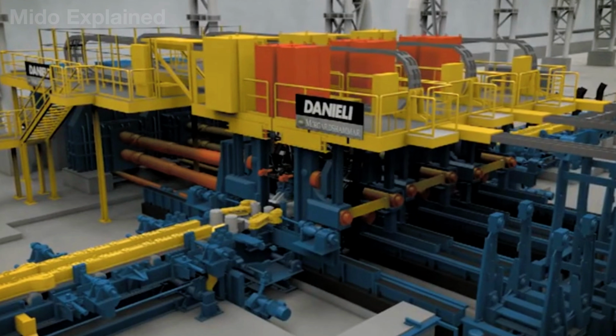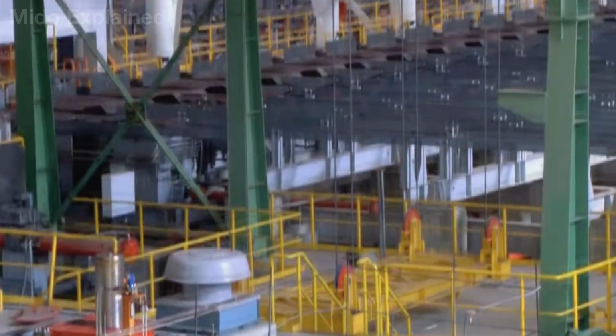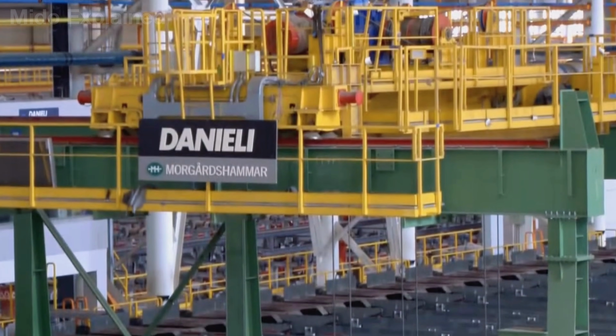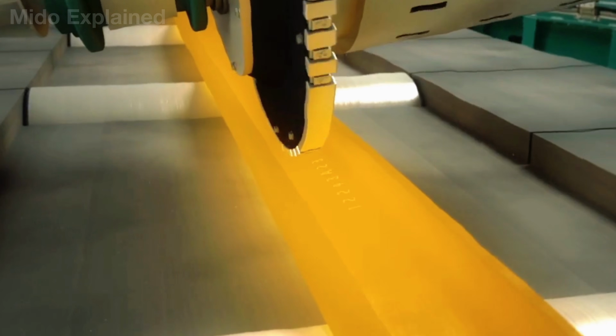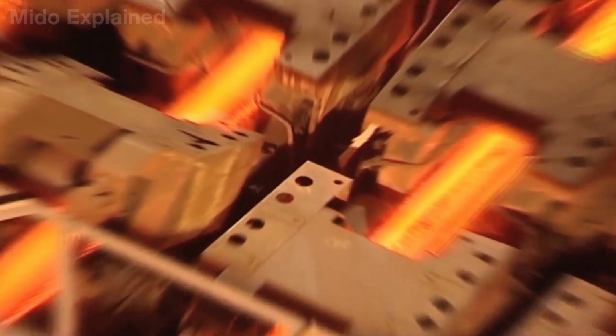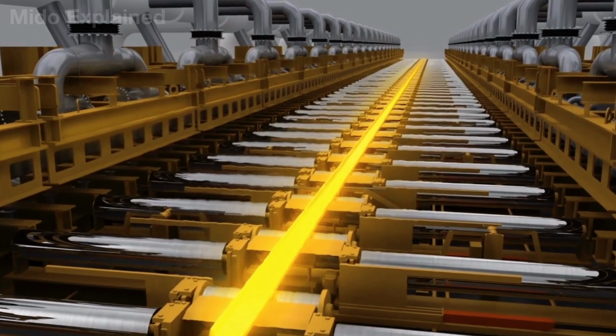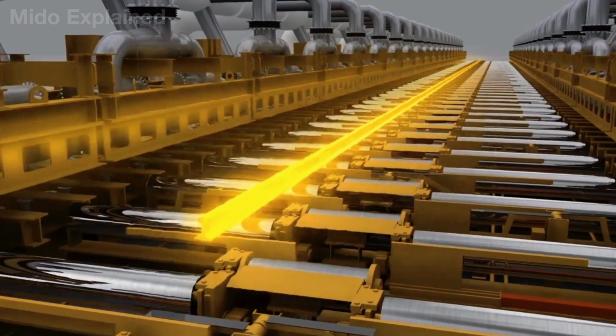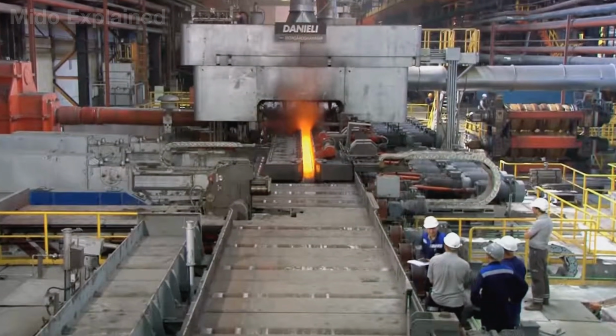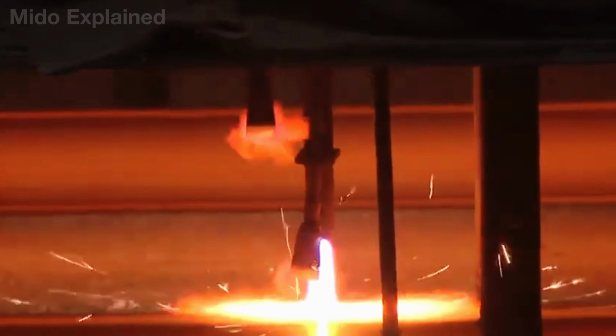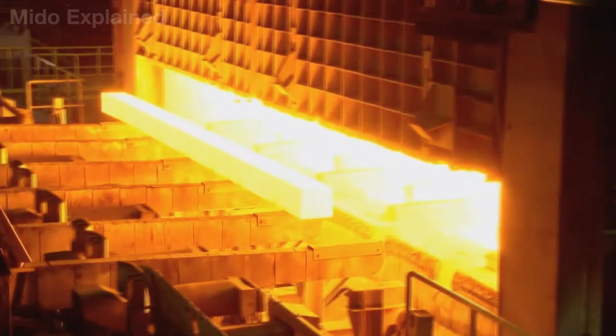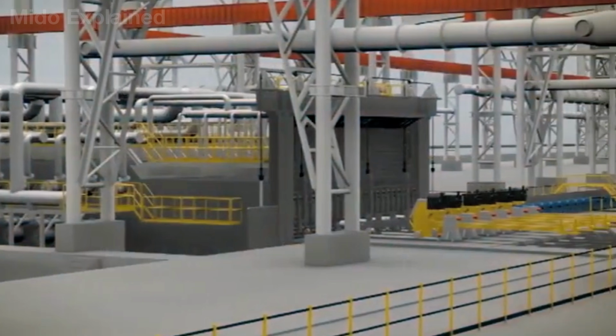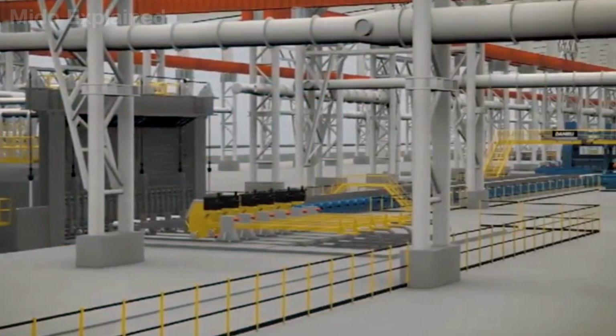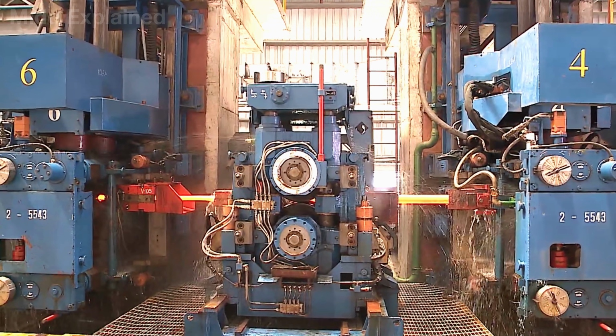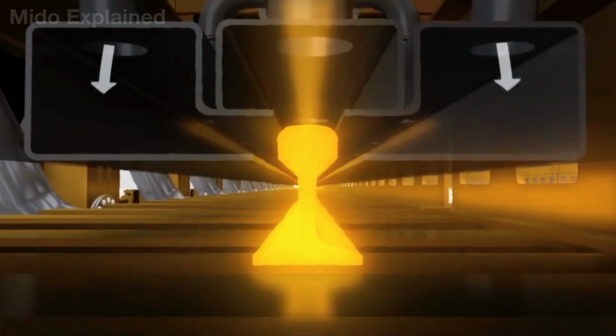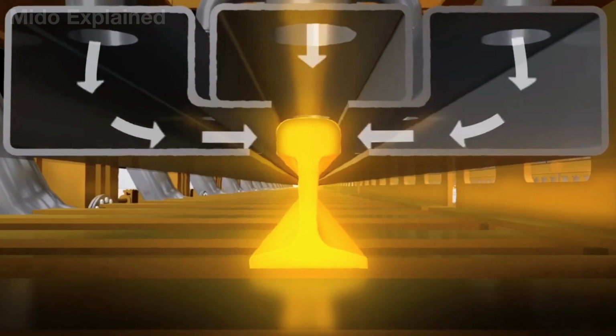Next are the intermediate and finished rolling presses. A modern rail production line typically uses from 10 to more than 20 consecutive rolling racks, each of which only changes the shape of the steel slightly. Instead of being pressed into shape at once, the metal is shaped step by step to avoid internal defects and help the material withstand pressure better. Through each rolling process, the rail head, rail body, and rail foot gradually appear clearly, creating the characteristic shape of the railway rail.